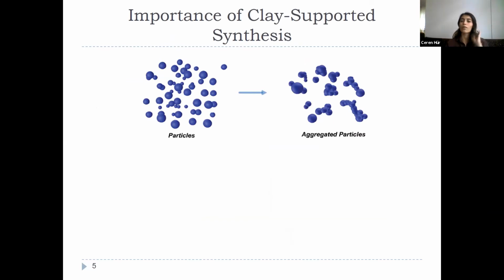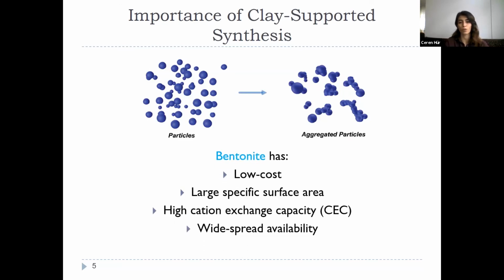Clay-supported synthesis is provided to decrease the aggregation of nanoparticles, and bentonite is an absorbent natural clay formed by chemical decomposition or degradation of volcanic ash and lava. It is widely used in many areas such as paper, food, and ceramic industry. Generally, it is non-catalytic. It has some benefits. These are low cost, large specific surface area, high cation exchange capacity, and widespread availability.